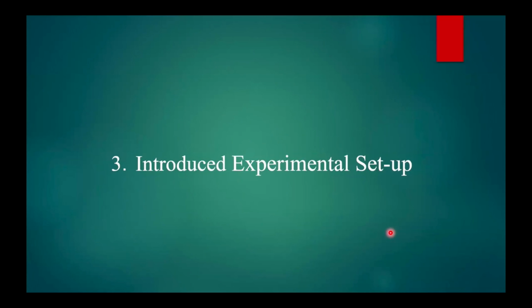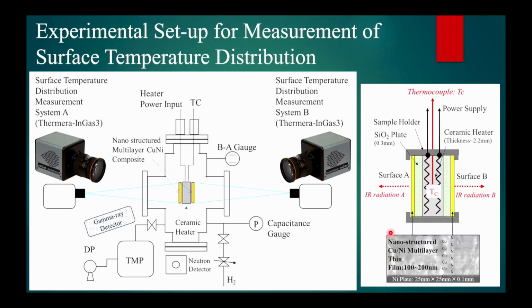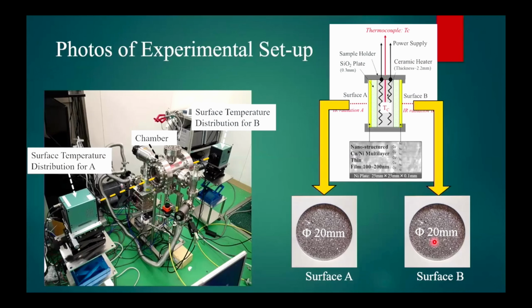And today, I'd like to present the surface temperature measurement. We measure the whole surface. We introduced a surface temperature distribution measurement system like this. We have two samples, so we introduced two surface temperature distribution measurement systems. This is a photograph of the experimental setup. We use this 25 millimeter sample, the circle here, and we can measure the whole surface with these devices.